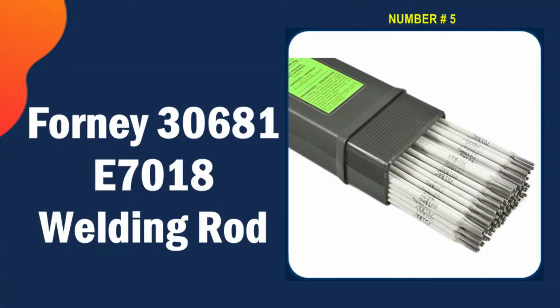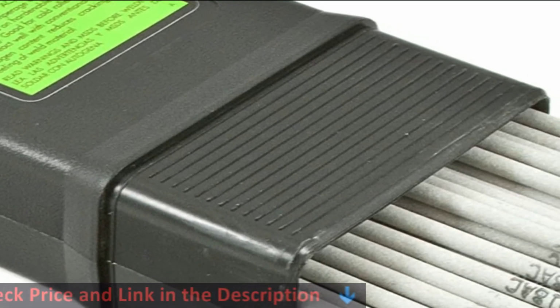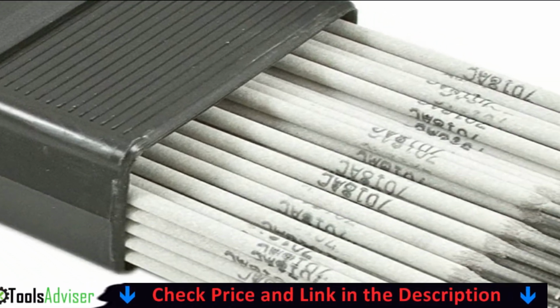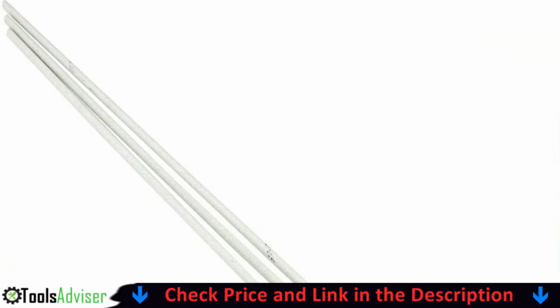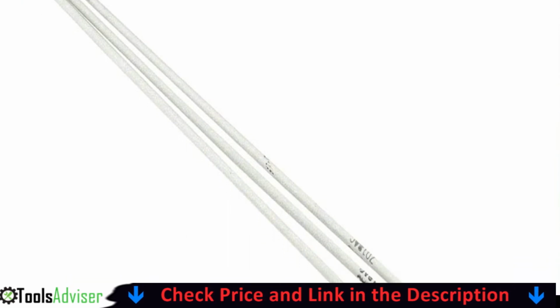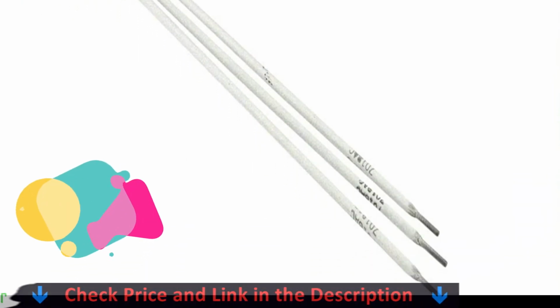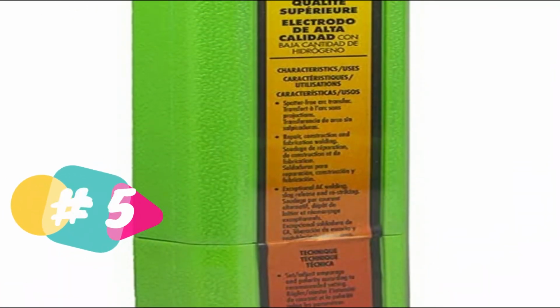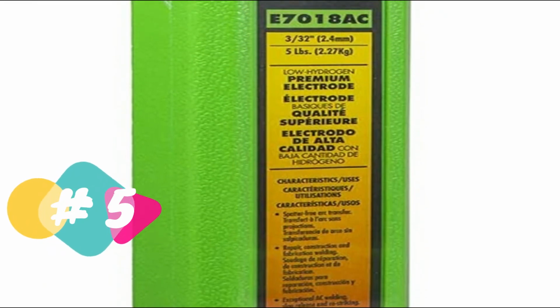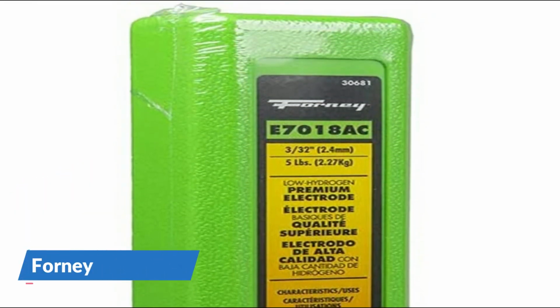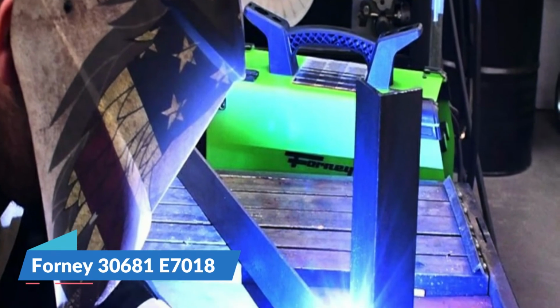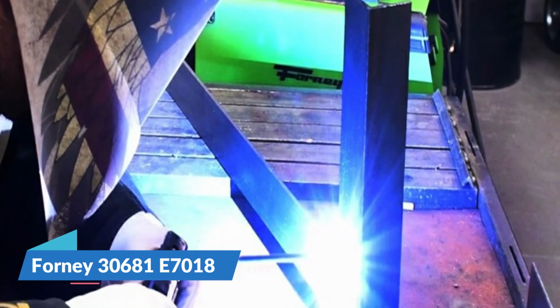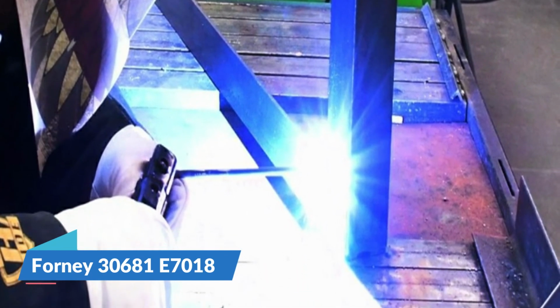Last in our best welding rods list is the Forney 30681 E7018 welding rod. These 7018 AC rods run really well. The slag will scorpion tail off your weld with a fresh rod out of the box, so you know the seal is good. I welded a piece of A500 to a slab of A36 and did not get any hydrogen cracking. They do prefer the high end of the amperage range for a clean strike, but that's pretty typical for a 7018. Two wonderful things really surprised me about these rods.